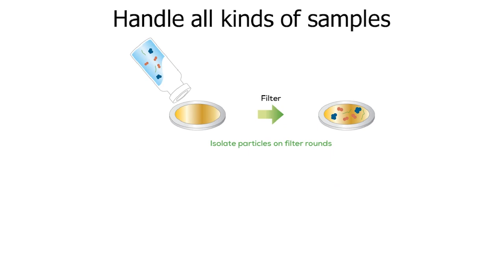Hound can handle a wide variety of sample types due to the highly flexible nature of the instrument. In our case studies, you're going to see a couple of different sample preparations. For particles in a liquid suspension, you can filter out the particles to isolate them on the surface of a gold-coated filter round. Alternatively, if you have a dry powder, you could simply spread that across the surface of that filter round.